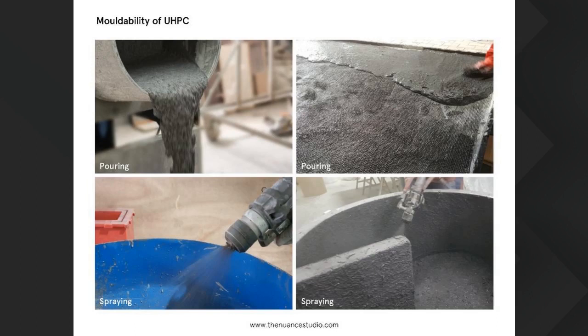So, can you pigment the premix with any stain available locally? Well, Shekhar, you would certainly be able to mix other pigments available locally. I'm not saying no, but I said we use this quality pigment to make sure that we have the best of the best quality. The pigments certainly alter the strength. In fact, the pigments increase the strength of concrete if used in the right manner, because they actually fill in the pores in the matrix. If you use excess pigment, it will also reduce the strength. But if you use them in the right manner, they wouldn't really lose strength, but will actually add to strength.